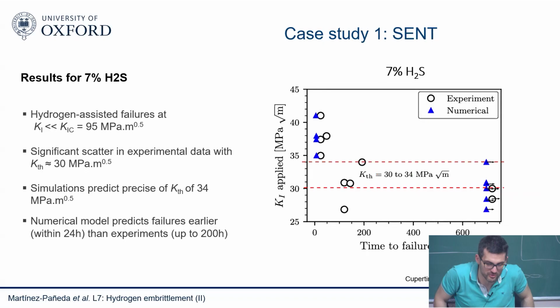And this is, by the way, for the 7% H2S. For the 7% H2S, they had much more scatter in the experiments. The experiments, again, are the circles. The open circles, you get significant scatter. So these ones fail quite early, but now they're failing later. Now they're failing in 200 hours. This one didn't fail. This one didn't fail. So there's plenty of scatter in the experiment. So now they're a bit worried. This problem is much more problematic for them. They don't understand why this one failed, why this one didn't fail after 700 hours, why this one failed after 100 hours. So somehow there's no correlation between load, time to failure, and so on. So this is a bit problematic for them.